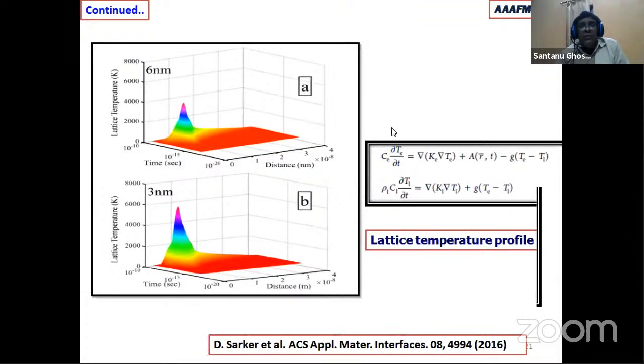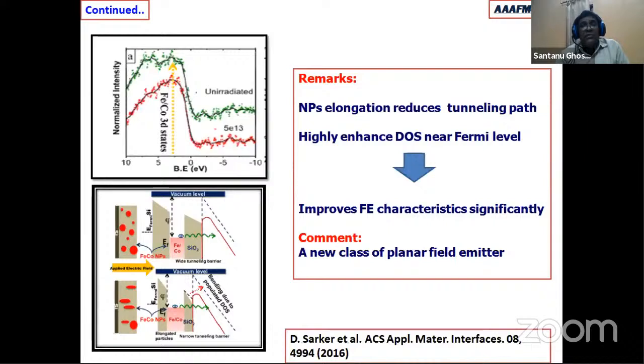So now again we went back to the thermal spike calculation, which I have already discussed, and for different particle sizes we have done the simulation, and one can notice the temperature of the lattice is almost in the 4000 to 6000 Kelvin range. So it's a very high temperature, which eventually leads to an elongation of the particle, of course, and a very high enhancement of the current density. So this is one aspect.